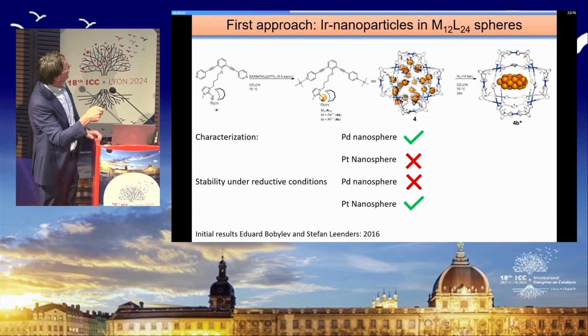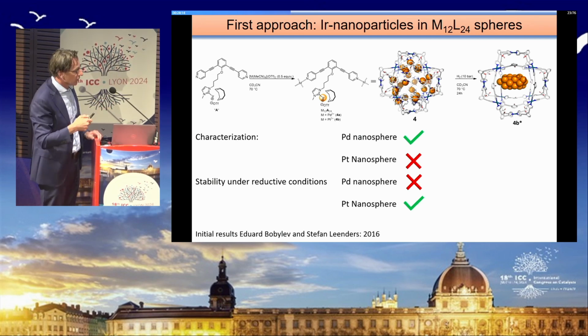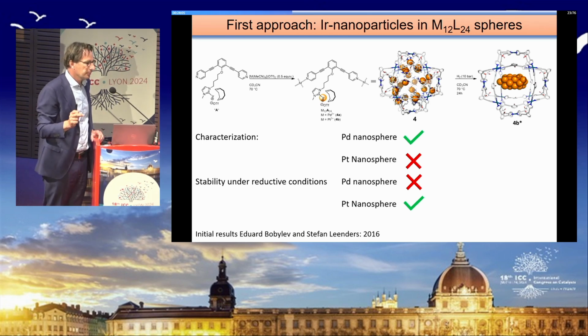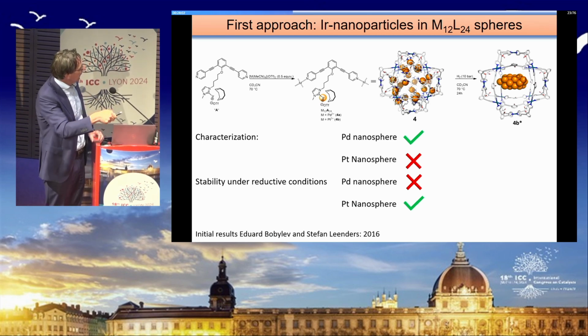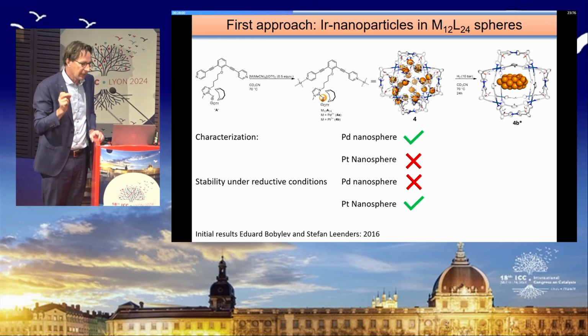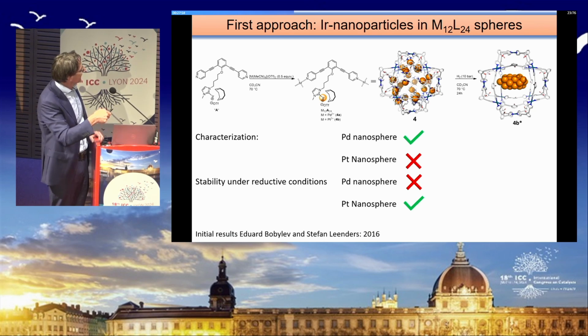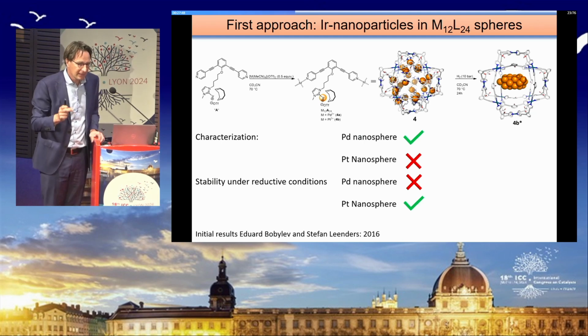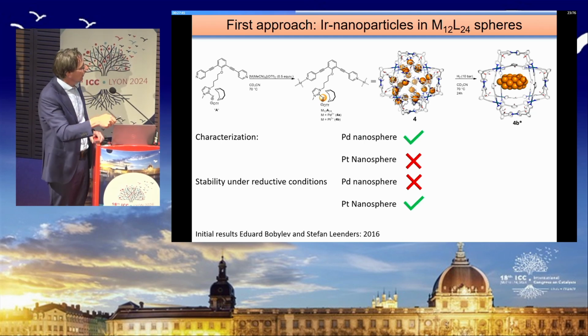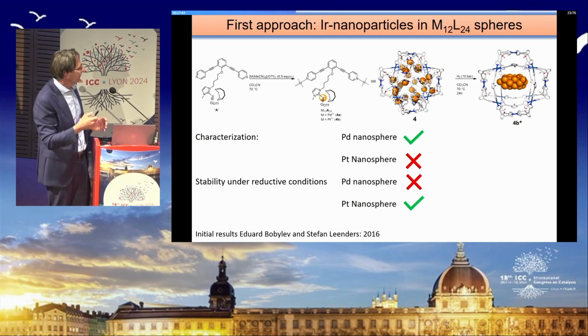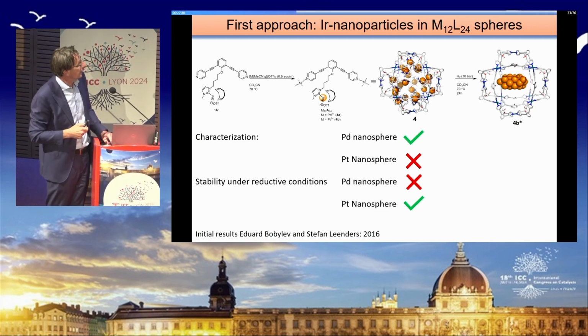So our initial approach was a covalent approach where we attached iridium complexes covalently to this ditopic ligand, and we can form the metal complex with palladium and with platinum. With palladium, we could clearly characterize the metal complex and the whole cage. With the platinum nanosphere, the NMR suggests that we have the compound, but we could not get MS data. And then we did reductive conditions to form nanoparticles, and the palladium nanosphere is not stable under these conditions, so it decomposed. And the platinum nanosphere is stable, but we could not characterize. So it was a little bit complicated here.